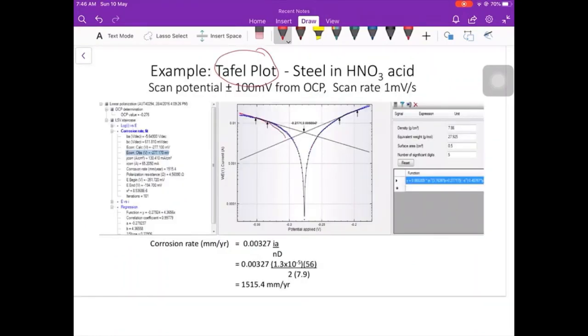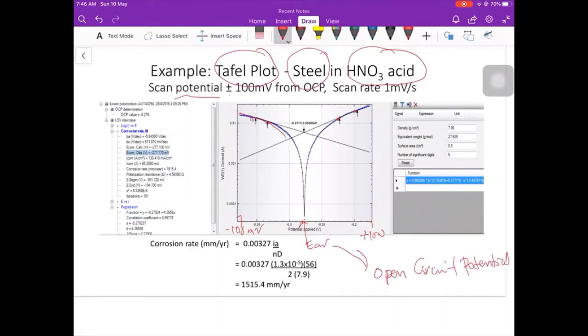Okay, so this is an example Tafel plot. You will get this V shape if you do this analysis, the corrosion of steel in nitric acid. You just scan the potential from plus minus 100 millivolt. This is negative 100 millivolt, and this is positive 100 millivolt from here. This is Ecorr, also known as OCP, open circuit potential, or corrosion potential. Once you get this V shape, you take these 2 points on both sides. You just plot a line here, the cross here. This value is Icorr. This Icorr will go into this equation. The value is in microamperes per cm square. Then you will calculate the corrosion rate.